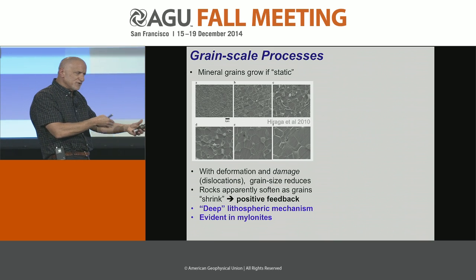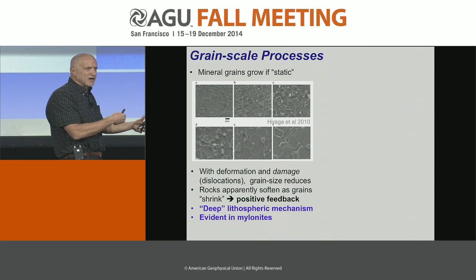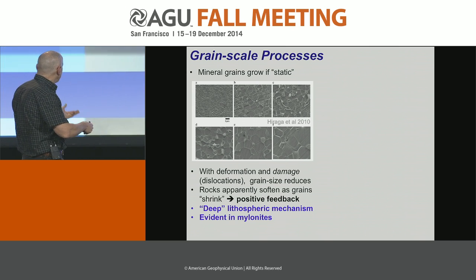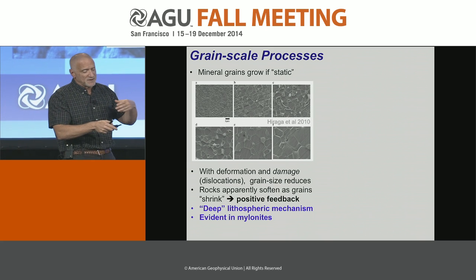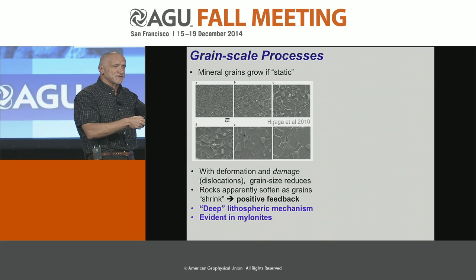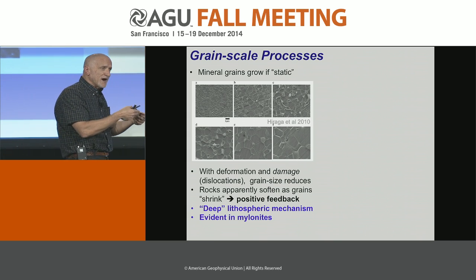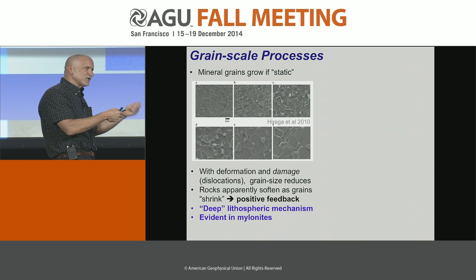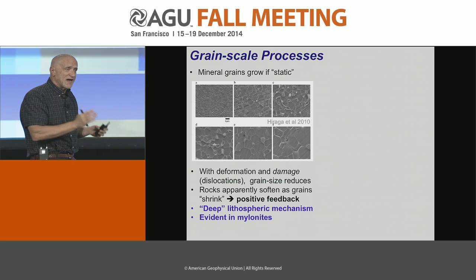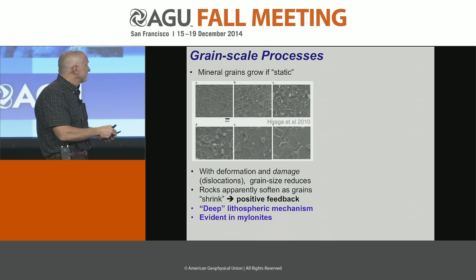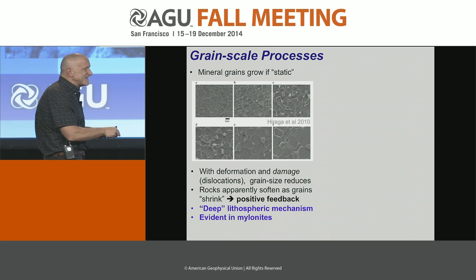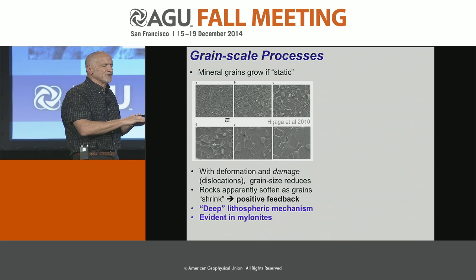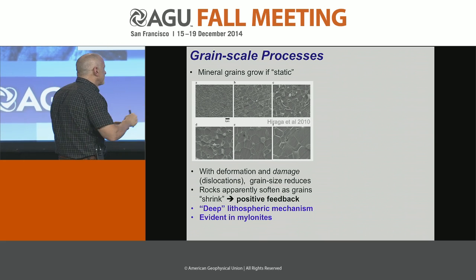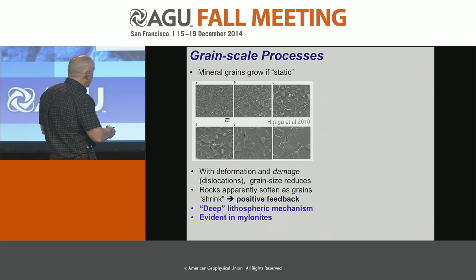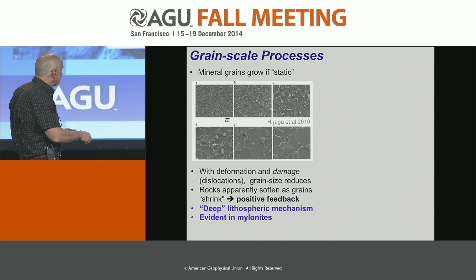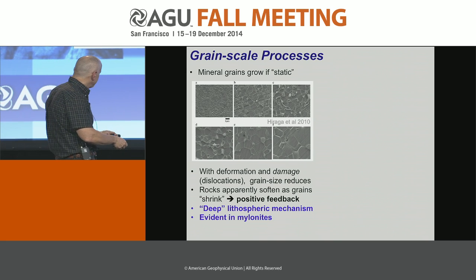the rock would soften because it's in diffusion creep, an efficient form of flowing if the grains are very small. And you get a positive feedback, because if you soften them and deform them faster, then you wind up grinding the grains down further, which will make it softer, which will continue to focus deformation. So it's that feedback we look for to cause narrow boundaries in this localization. And this may be appropriate for this deep lithospheric mechanism, below the brittle-ductile zone, in the deeper, strong, cold ductile region of the lithosphere. And it also appears to be evident in the mylonites that we see pervasively in these regions of high deformation.